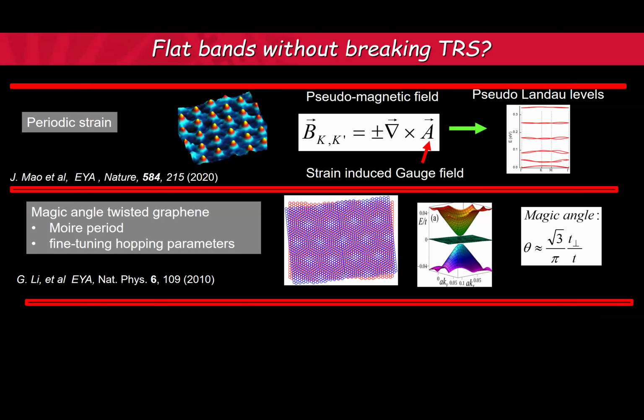The other case that I know about is applying a periodic strain. We've done that with graphene. This is buckled graphene, and you can create a periodic strain lattice. Strain does give rise to a pseudomagnetic field, which has pseudo-Landau levels, and we have measured them here. The strain gives you a gauge field, and if it has a special form, you can get a pseudomagnetic field, pseudo-Landau levels, and you can map everything. You get a flat band that you can map onto Landau levels.